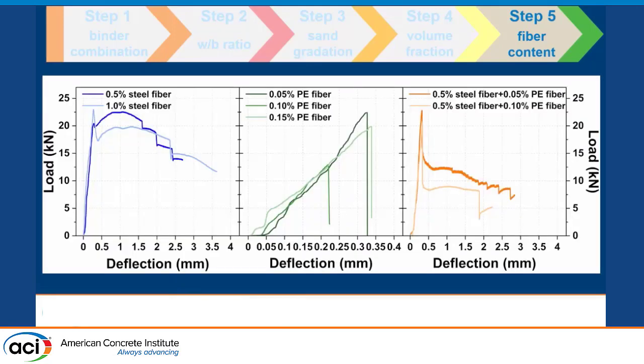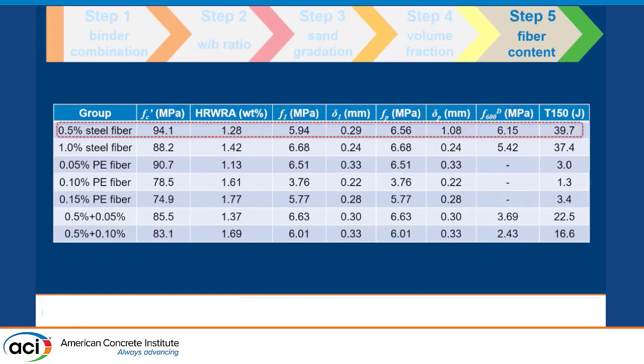Further, we did the flexural performance evaluation on these nHPC samples with various fiber contents. As we can see here, steel fiber gives the nHPC sample strain hardening after the first crack, while the PE fiber doesn't. And we can also see that the nHPC sample with the combination of steel fiber and PE fiber has only half of the post-cracking tensile strength with respect to the nHPC sample with steel fibers only. So here are the detailed results, and the optimum fiber content can be determined as 0.5% of steel fiber.